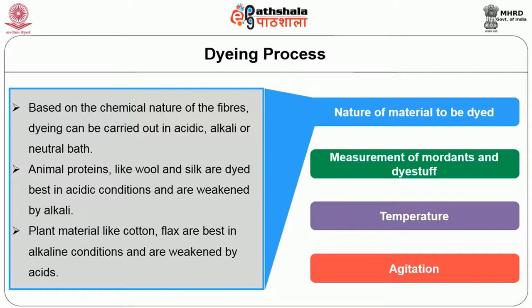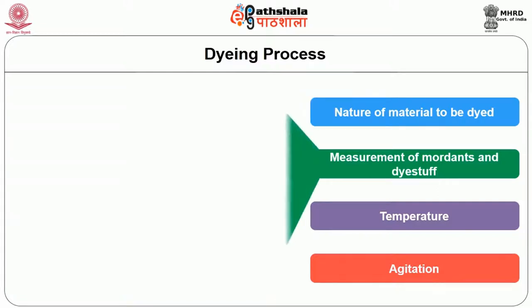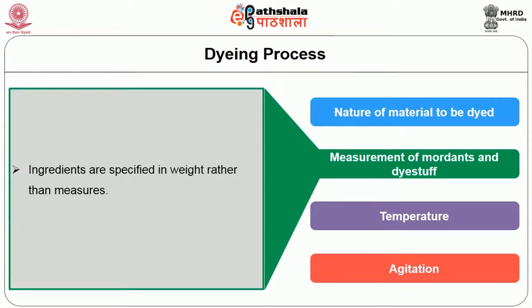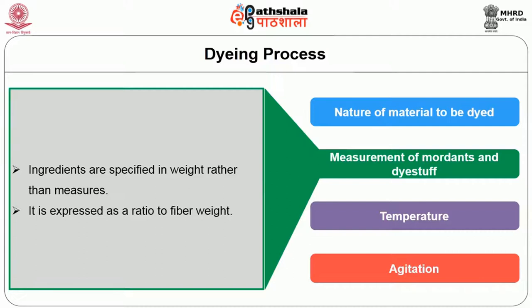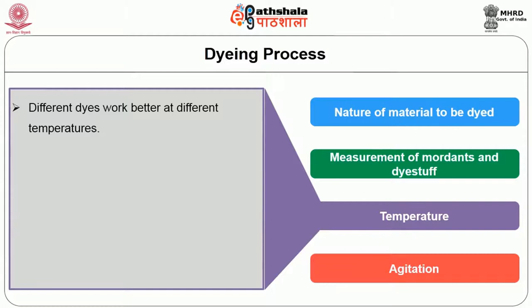If cotton is dyed in acidic condition, it is best to end with a weak washing soda bath to restore the fibres to slightly alkaline condition before they dry. Ingredients are specified in weight rather than measures and expressed as a ratio to fibre weight. Temperature is also a key factor — different dyes work better at different temperatures.